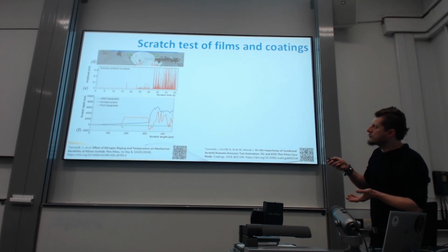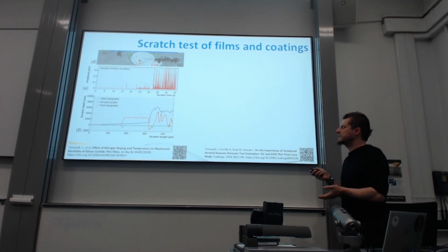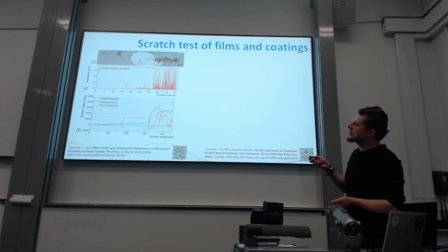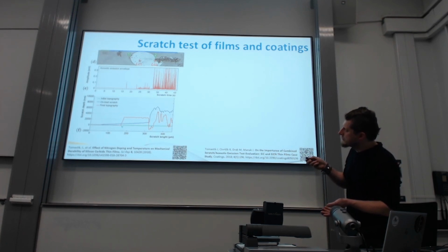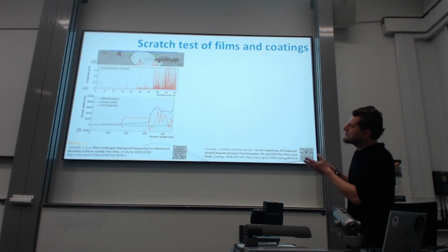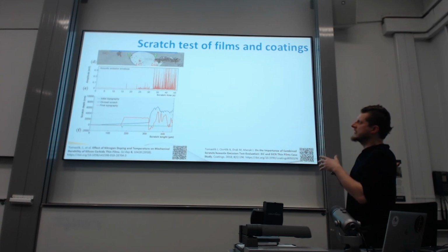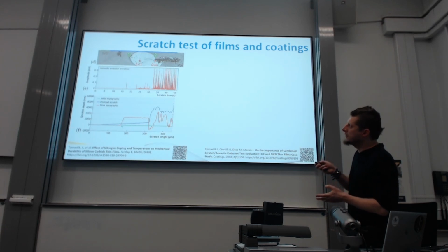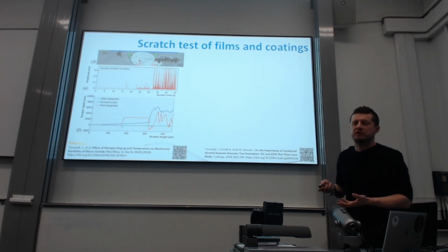And then we have gross spalling, destruction. If you were an experienced user of a scratch tester, you could say there's backward spalling, something like that, because it looks like that. So you would guess that in that moment something happened in the backward part. So the critical load is not this, it's probably this. But because of backward spalling, this substrate cracking was revealed; you wouldn't see it otherwise. This is one scratch track out of, let's say, 10; in 2 cases this happened, and in the other 8 cases this backward spallation didn't happen. So I didn't even know about substrate cracking.